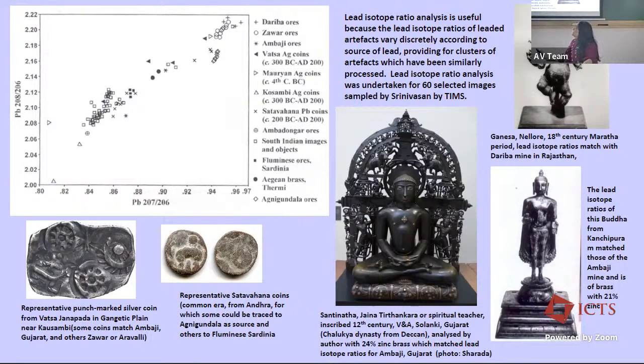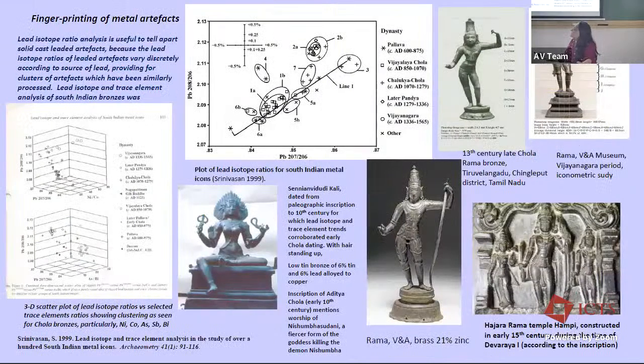And Dariba also is a very big source of silver. We talked about Zawar as having been exploited quite early for zinc, but from Dariba you also had a lot of silver being exploited as a lead zinc source, and they used the cupellation process, which is another method of extracting, purifying the silver from lead silver ores, because the lead tends to get oxidized out and the silver gets enriched. And that's also, in fact, the basis of the fire assay process.